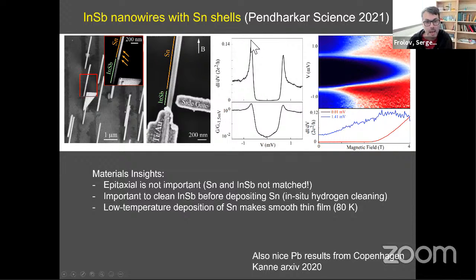This is the induced gap in this material. You see the same peaks as I showed you before. They're at higher voltages, and inside the peaks, conductance is very low. So we call it a hard gap. Now this hard gap survives to pretty large magnetic fields, at least a couple of Tesla. There is no current at zero bias. So these are all good news for having a good starting point for Majorana experiments, maybe even for qubits.